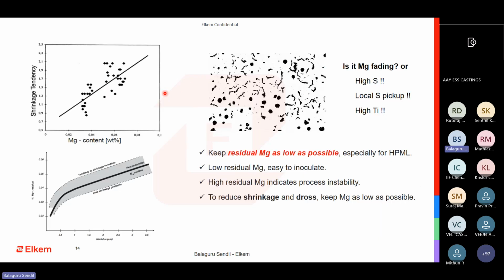As I told, with respect to shrinkage, magnesium is highly shrinkage-prone, and when you have a higher residual magnesium of 0.045 or 0.050, your probability of shrinkage is very high. So you need to compensate with additional risering or slightly bigger risering in your casting profile, which is not an ideal situation. If you look at it, 0.02 to 0.04 is an ideal range when it comes to shrinkage. We don't want to go beyond it.